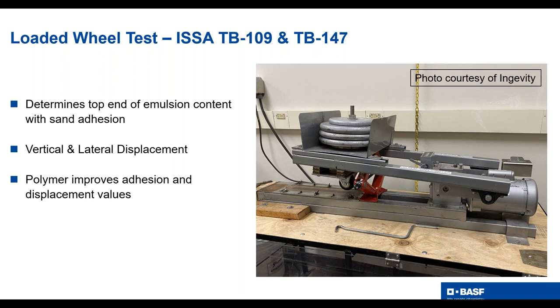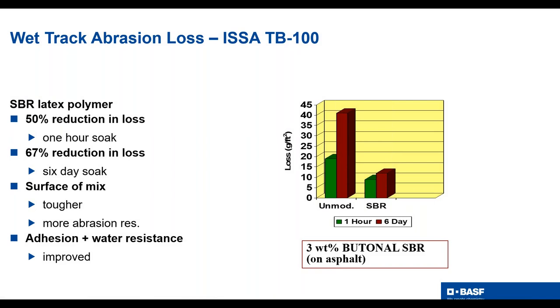Next, though, I want to get into the wet track abrasion. This test has been around for a long time, especially the 1 hour test, which I want to hit on a little bit of definition. The 1 hour test has been used in slurries for a long time. And you'll notice that unmodified versus modified, the green are the 1 hour tests. And you can see with the green bars, if you have unmodified, you had a pretty good grams per square foot loss on this. But with the SBR, you had about a 50% reduction in loss.